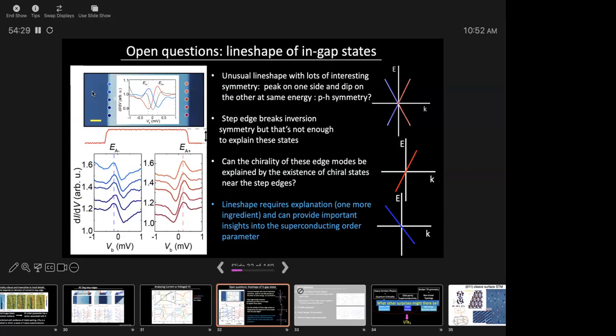Wouldn't that imply that the results should be somewhat different? Or is it the method by which we preferentially tunnel? No, that's got nothing to do with it. That's got to do with the way tunneling happens. You can just think about it geometrically. If you have electrons just spewing off the tip, then certain electrons going in certain directions would not hit the edge. Normally you don't see this because you don't usually see chiral edge states. If you have electrons at positive K, you also have electrons at negative K. But this is a very rare situation where you actually have chiral states. So maybe we're seeing something that hasn't been seen before in tunneling, in terms of momentum selectivity. Very hand-waving. I'm not comfortable.